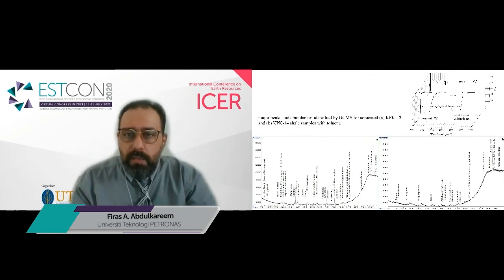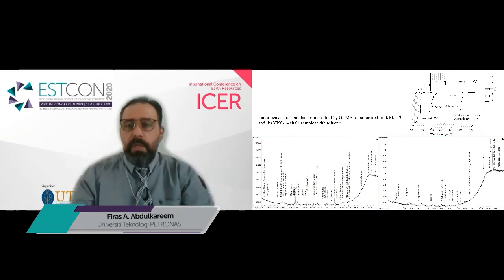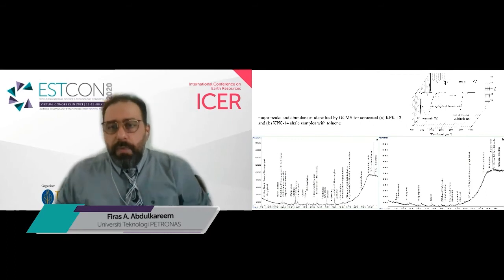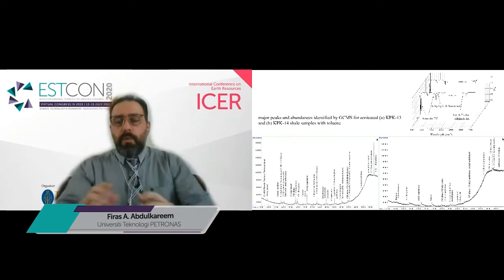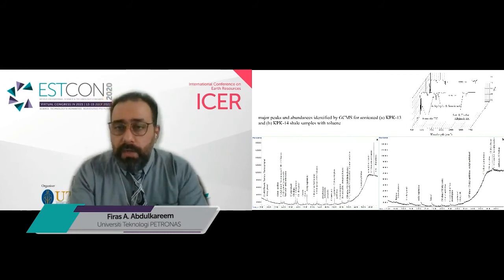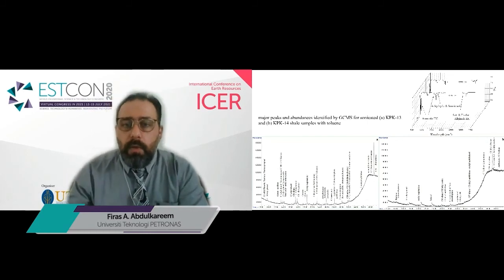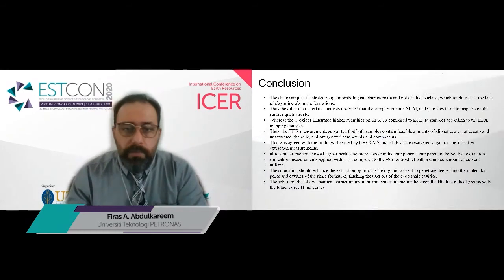And as we can see here, more or less the aromatics and anhydrides from using the ultrasonic process are somehow typical to the hot reflux process, but with a wider range and more productivity of hydrocarbons extracted.